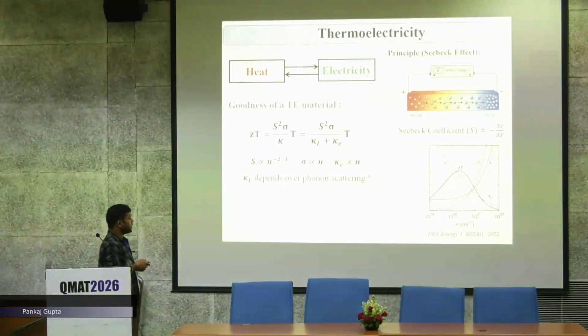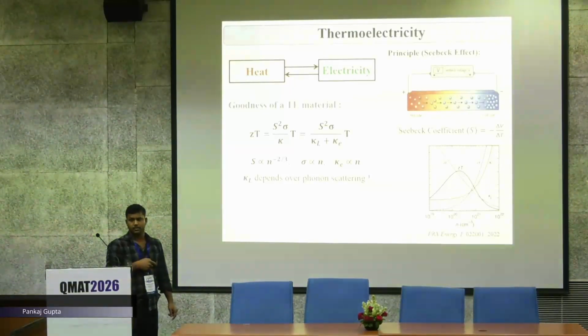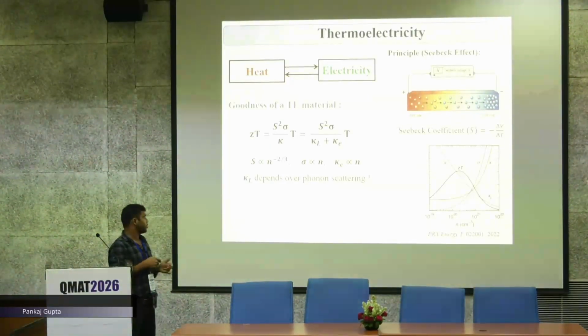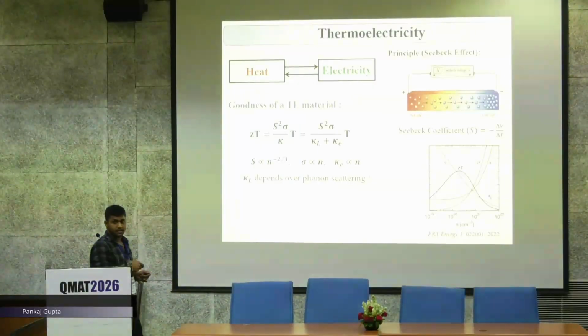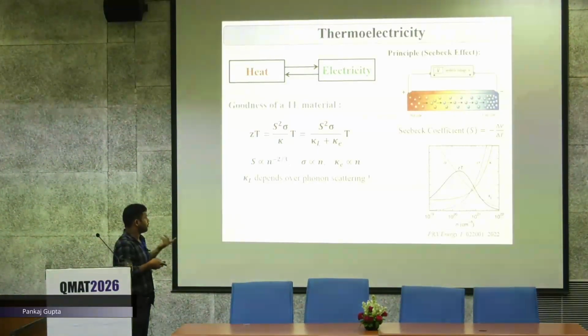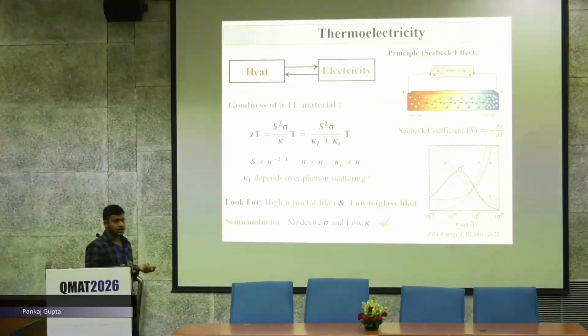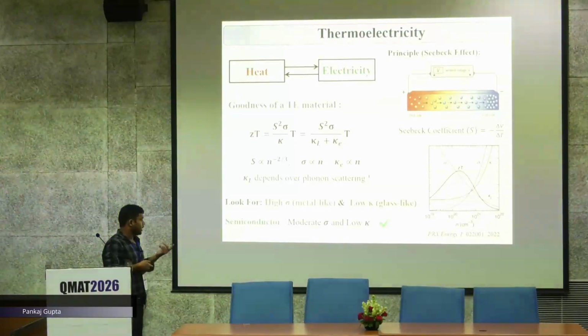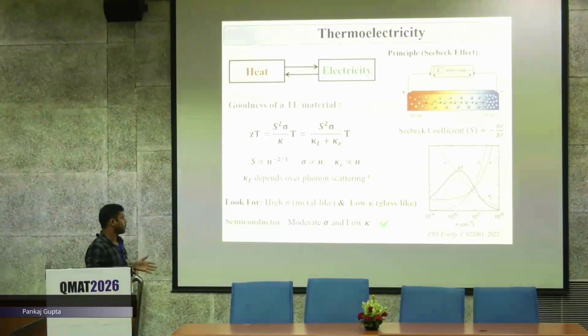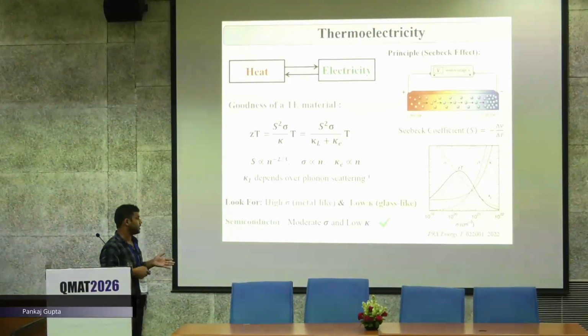But one good thing is that this KL is the phonon part, the lattice part of the thermal conductivity, which depends on phonon scattering. So by tuning the carrier concentration and the lattice thermal conductivity, we can get good thermoelectric properties. In thermoelectrics, we look for a material which has metal-like high electrical conductivity and glass-like low thermal conductivity, and getting this is very challenging. So we choose a semiconductor material, where we have moderate electrical conductivity and low thermal conductivity, and we can tune the electrical conductivity further by doping, as we all know in semiconductors.